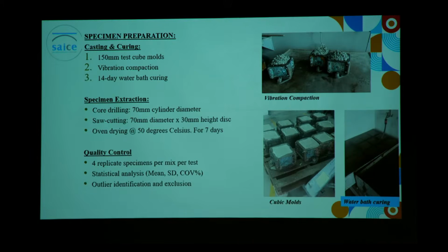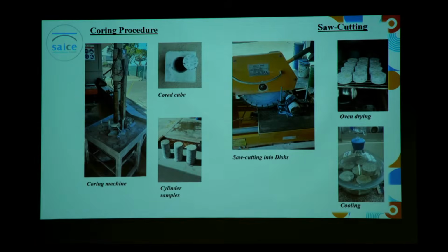So the procedure followed was as follows: to cast in cubic molds, and then follow a standard procedure of vibration, and then curing in the water bath for an early age of 14 days. And then the specimens were extracted, and then cored and saw cut to specific dimensions according to standards, and then it would follow the durability testing of our specimens. So this was just our procedure followed. On the far left-hand side is the procedure of coring our specimens, followed on the right-hand side by the saw cutting of our materials in the lab.